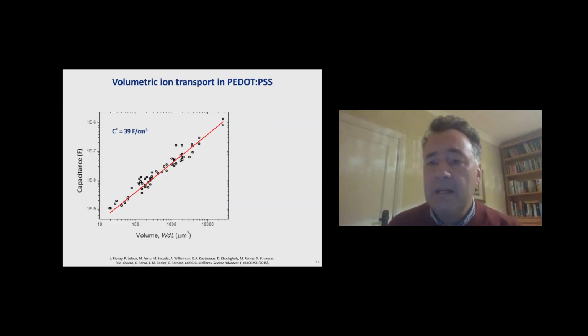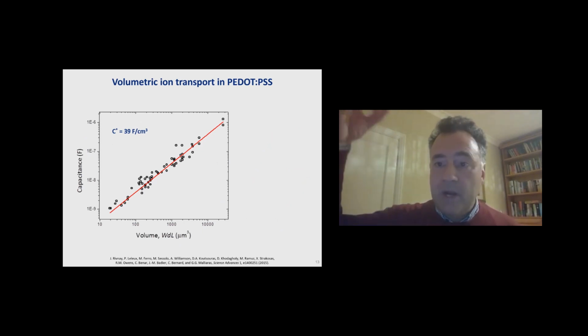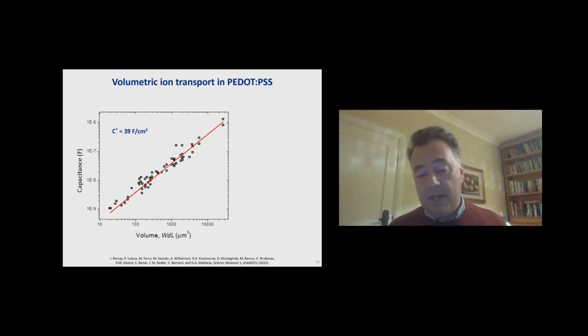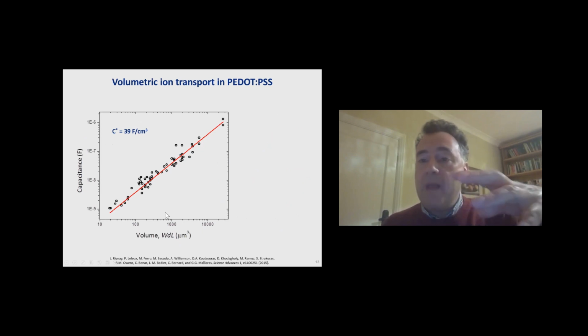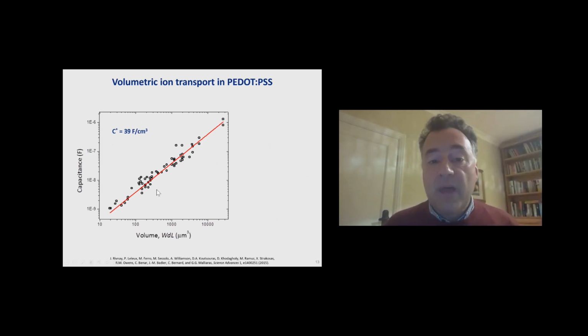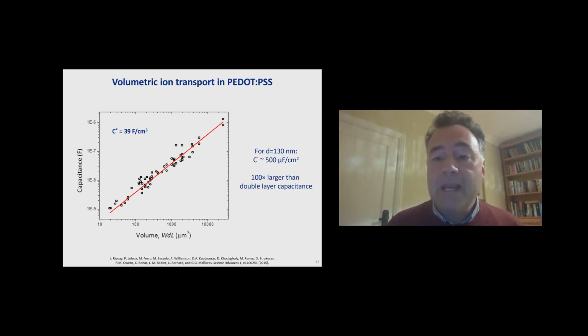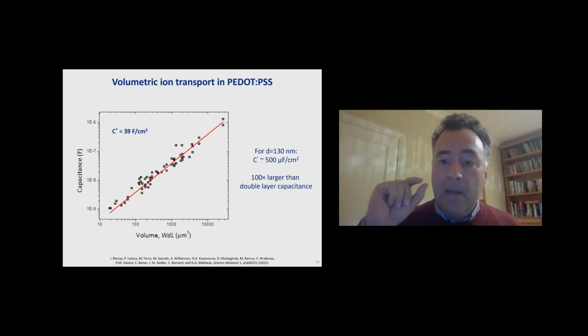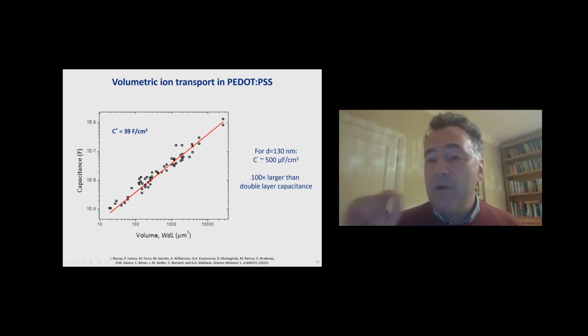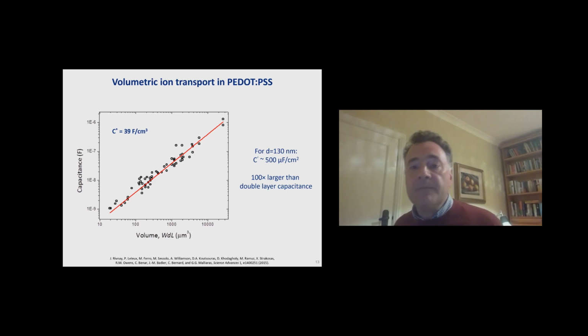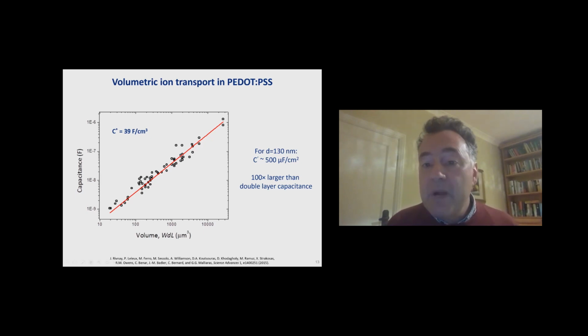Turns out there is an ideal material for this purpose that has perfect volumetric conduction. Ions can go into the volume and couple very efficiently with electronic charge. And the way this manifests itself is in a capacitance that scales with the volume of the material. The larger you make your electrode, or the thicker you make your electrode, the higher the capacitance. What does that mean? That means that if you just coat a metal electrode with a film of this polymer that is just 130 nanometers thick, a very, very thin material, you're going to have an increase in the coupling between ionics and electronics of 2 orders of magnitude.